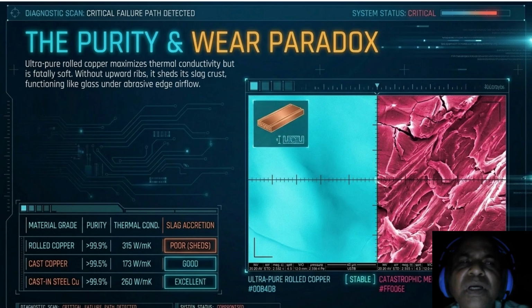While rolled copper is more than 99.9% pure, its slag accretion is rated as poor. Conversely, cast-in-steel copper, though slightly lower in pure conductivity, provides excellent slag retention. This means that by chasing the highest possible purity, we are actually inviting faster erosion, because the material cannot hold a protective layer. This lack of protection creates a massive diagnostic blind spot in our monitoring system. If our materials are failing, we need to know exactly when and where. But our traditional sensors are lying to us.